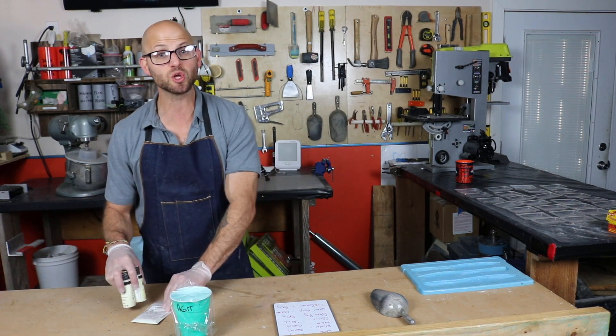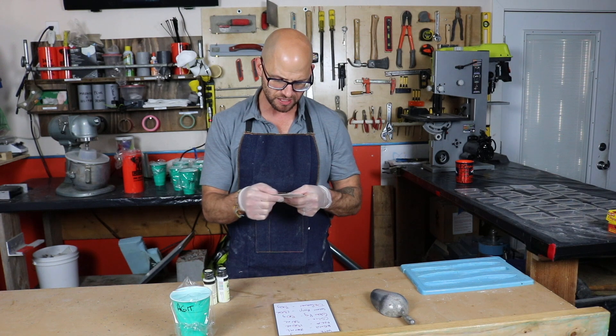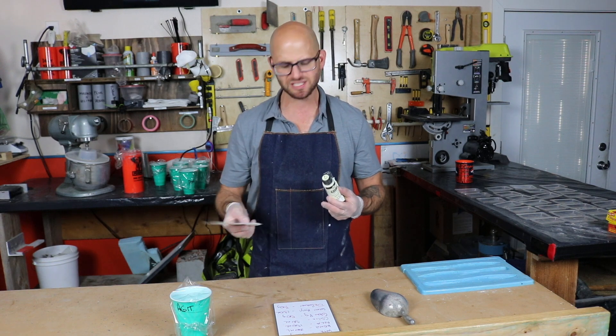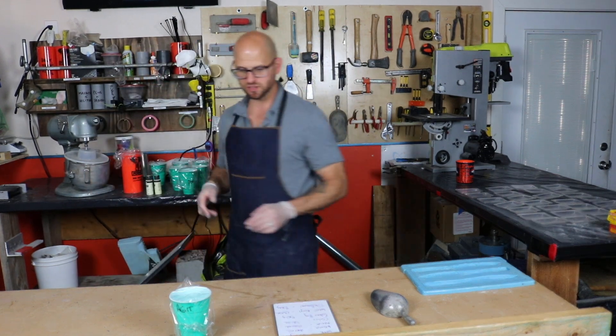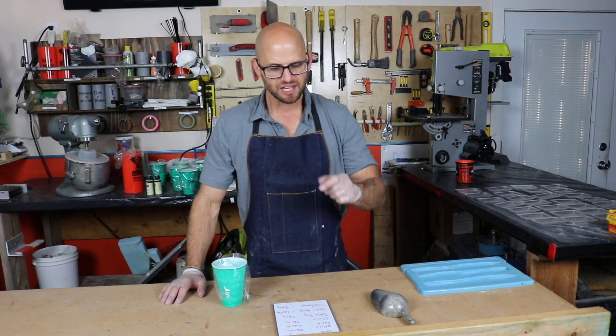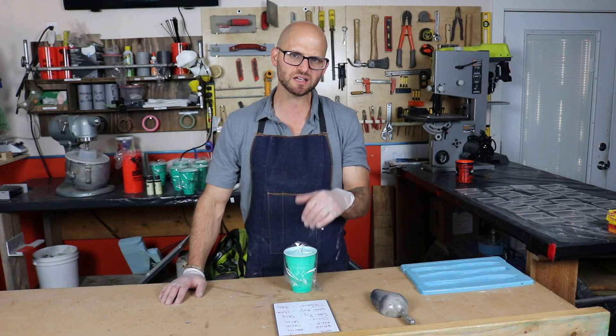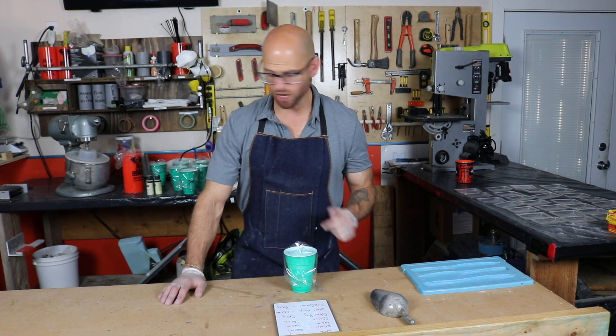Next I'm putting in my glow product: 60 grams of a sky-blue glow-in-the-dark pigment powder — my favorite color is blue. I'm also using that glow product from Home Depot for instantaneous glow lasting 10 to 15 minutes, but this pigment powder will last nine to twelve hours. Finally, I'm using a defoamer — about 30 grams — because acrylic polymers tend to increase trapped air and big air bubbles in the grout, and I want to knock that air down to create a denser mix.